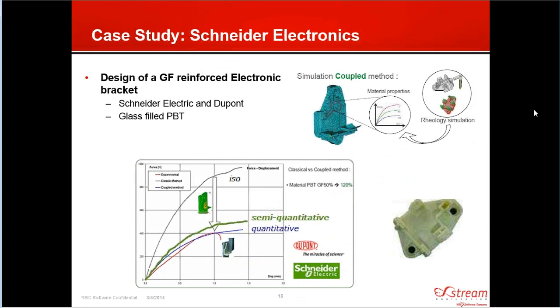So here's another case study example. This is a case study done with Schneider Electric on an electrical bracket that they were looking at manufacturing with a glass-filled PBT. So what you see here is a couple of different curves. You've got the red curve, which is their test results for one loading scenario. You've got the black curve, which was their isotropic approach that they were using before Digimat, so really not giving a very accurate picture of stiffness at all. And then you've got your two other approaches, which are labeled here as the semi-quantitative and quantitative approach.